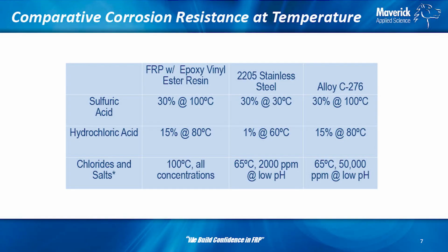Hydrochloric, very similar. You're looking at 15% and 80 degrees C. The point that I want to add is if we went from a mid-grade vinyl ester to the Novolac vinyl ester, instead of 15 it's going to go up to, I think, 35, 36, 37, what Kevin pointed to earlier. HCl is a service that FRP is good for. I've seen FRP tanks that have been in service over 30 years, and I can't say they're pretty, but they're sufficient. They're suitable and still in solid service.